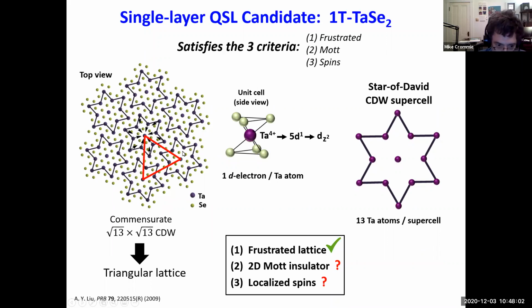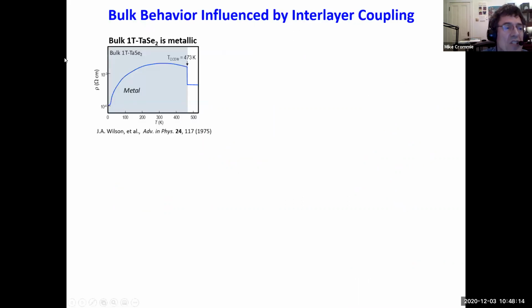And as you can see, that's a triangular lattice. So this material does satisfy this first criterion of a frustrated lattice. But is it a 2-dimensional Mott insulator? That's a trickier question to answer. One of the reasons why that question is hard to answer is because, for example, if you look at the bulk material of TaSe2, 1T TaSe2, it's a metal, and that's about as far from a Mott insulator as you can get. And so here it is. You can see that it's a metal.